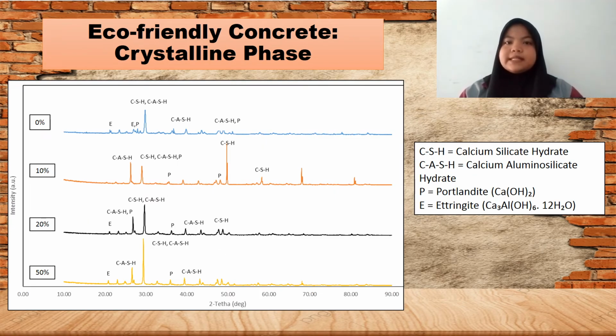Eco-friendly concrete crystalline phase. XRD analysis is the method to find mineral composition like calcium silicate hydrate, calcium aluminosilicate hydrate, portlandite and ettringite present in concrete. The higher peak for the control sample is the same as 20% and 50%, which contain calcium silicate hydrate and calcium aluminosilicate hydrate, but different for 10% of GRTW, which has only calcium silicate hydrate. The peak rate by the diffraction of portlandite shows the same intensity in all types of concrete. As the cement content was lower, this supports that the particle effect of mixed ceramic will accelerate cement hydration.